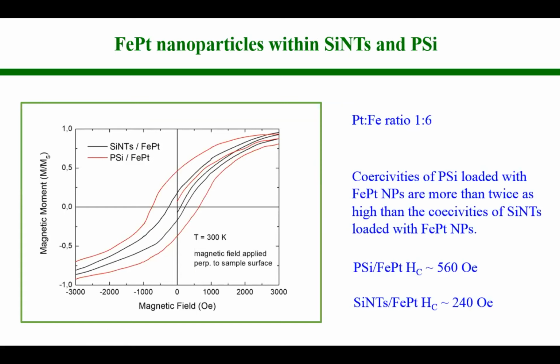So this comparison here shows magnetization measurements of silicon nanotubes filled with iron platinum and porous silicon filled with iron platinum. Porous silicon is the red curve, and you see that the coercivity for the porous silicon composite is much higher than for the silicon nanotube composite. And one reason is the bigger particle size.